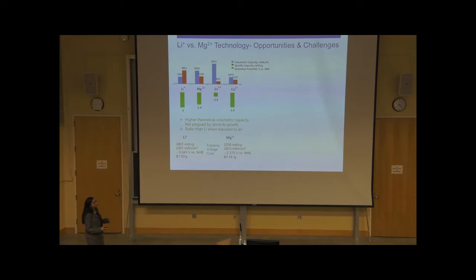Like I mentioned, lithium-ion batteries are limited by their energy density and their cost, and they are dangerous because they can catch fire. One way to enhance the performance of lithium-ion batteries is to replace these monovalent lithium ions with multivalent ions such as magnesium, zinc, and calcium. By doing that, we can get much higher volumetric capacity. They are not plagued by dendrite growth, which means they are much safer. They don't catch fire. And they're known to be safer than lithium when exposed to air.